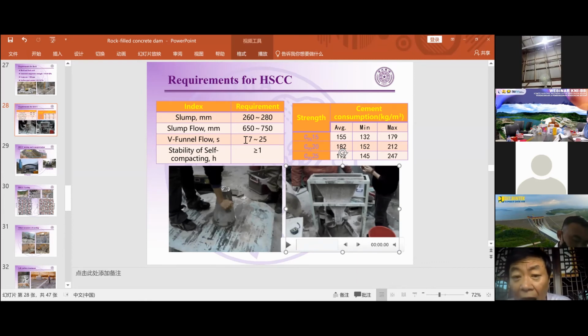And another aspect is how we can obtain that good workability. This is due to two reasons. One reason, we must use a very, very good superplasticizer. And second, in this concrete, the volume of the coarse aggregate is smaller. So we use more sand, and we use more mineral admixture, and we use some more powders. So the dosage of the self-compacting concrete is different from the conventional concrete.